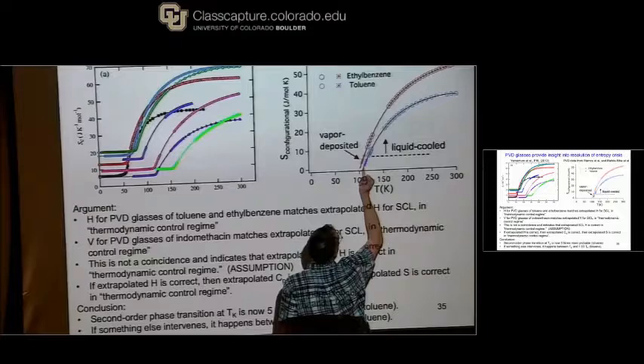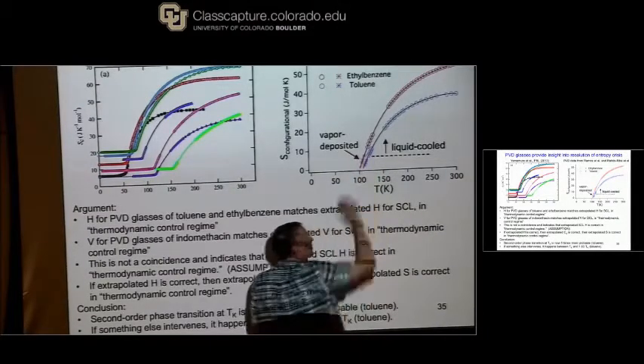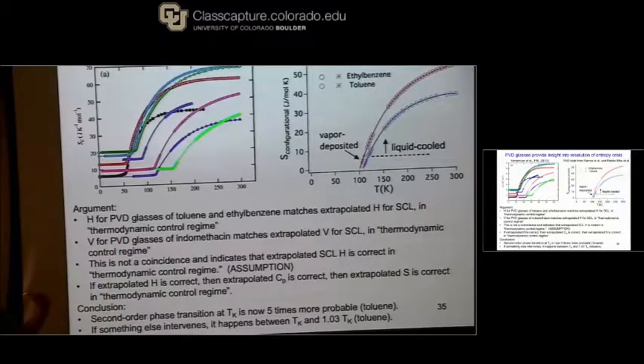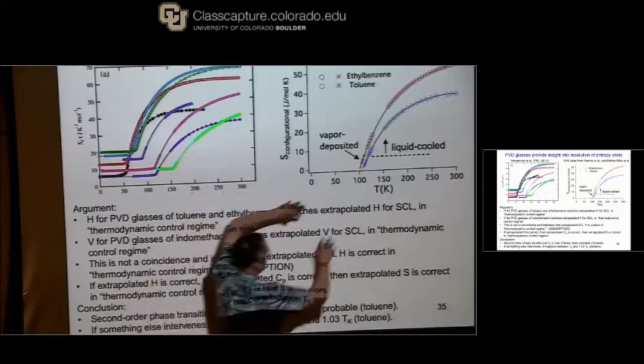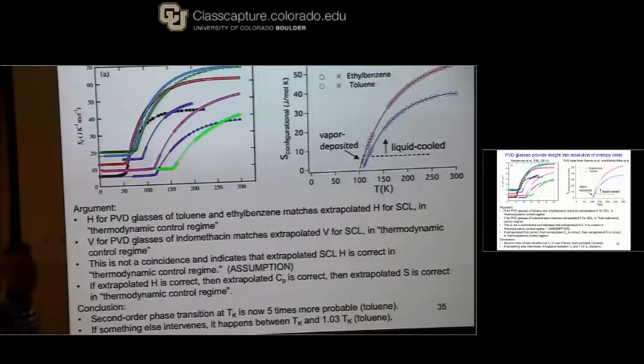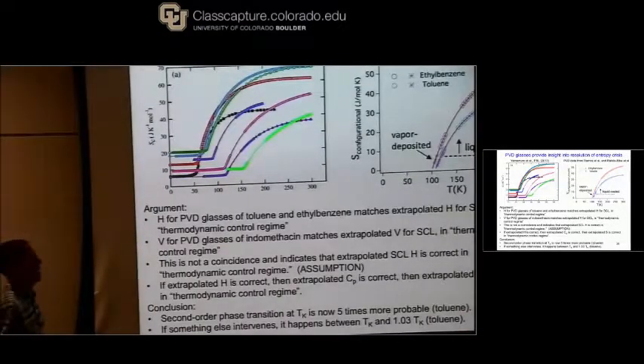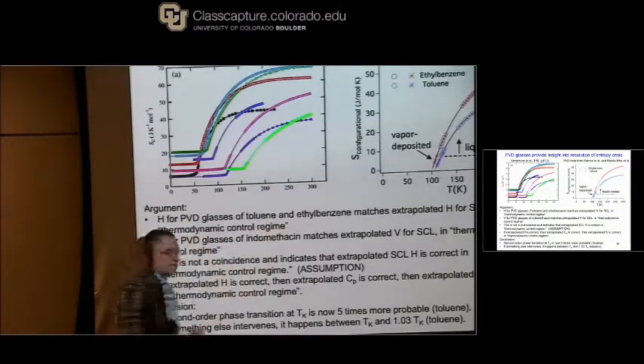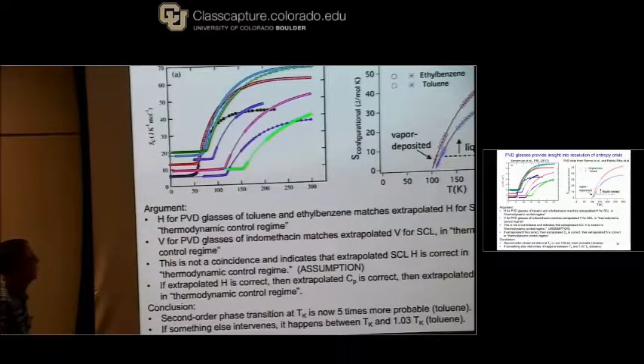So in this construction, this is TK for toluene, this is TK by extrapolation of the supercooled liquid. Okay? So I'm taking that from Yamamuro, and now I'm going to put points for vapor deposited materials on that line. And I'm going to describe my chain of logic here. I just told you that the enthalpy for vapor deposited glasses of ethylbenzene matches the extrapolated enthalpy for the supercooled liquid in the thermodynamic control regime. I showed you that data. I didn't show you the data for toluene, but the same thing works for toluene. I showed you that the volume for PVD glasses of a different system matches the extrapolated volume for the supercooled liquid in this thermodynamic control regime.